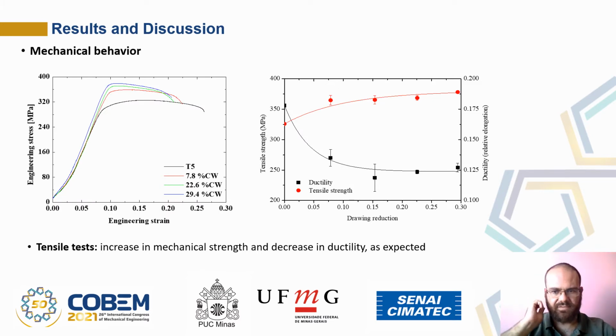So, the results: mechanical strength behaved as expected. As we increase drawing reduction, hardness and strength go up while ductility goes down. The data is summarized in the second figure of this slide, which shows that after approximately 20% of reduction, the loss of ductility and the increase in mechanical strength is more or less stable.